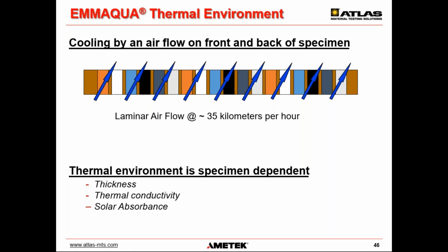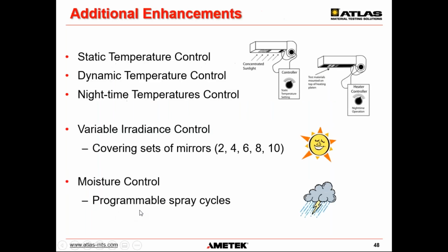standards. As I mentioned, we cool the materials that are on exposure with airflow in the front and back. We almost always use an unbacked exposure for this. You have to be a little bit careful because the samples need to be flat for this type of exposure. The maximum height of the sample is 6 inches because that is the width of the target board. And also, you have to be careful about samples that are too thick or really, really heavy because the thermal environment is going to be dependent on that thickness of the sample, how much air it requires to pull away some of that heat, the thermal conductivity, and of course the solar absorbance of the sample itself.